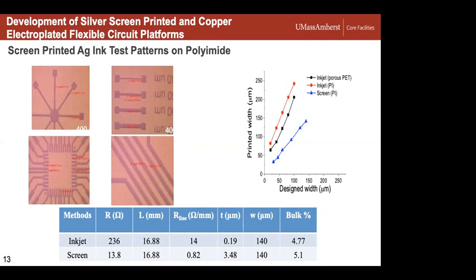So the images on the top left show 4 different examples of different line widths and patterns. You can see we get very nice sharp edges, very crisp, very clean, and you can get patterns down to 20, 10 micron types of features. Very typically 50 microns is very doable and reproducible, but you really have to work at it to get that optimal. But we do show some pretty sophisticated patterns here.